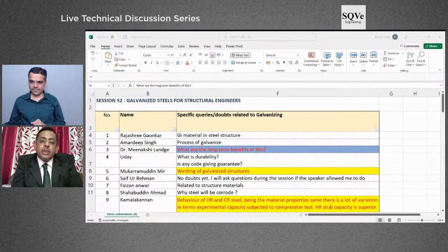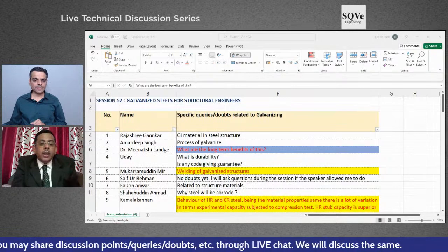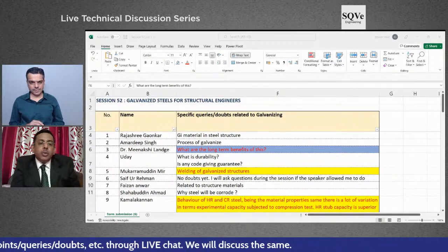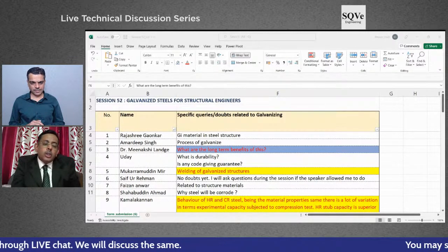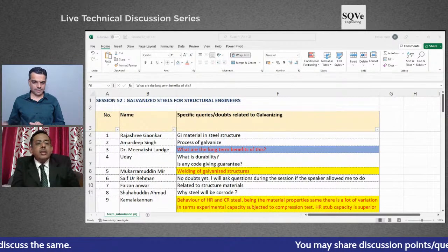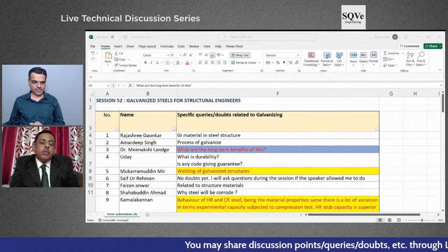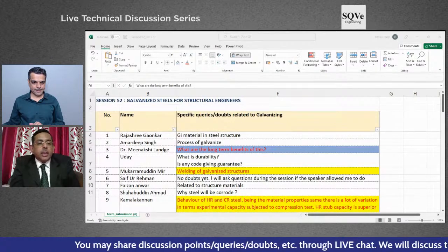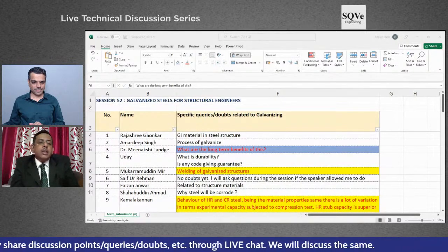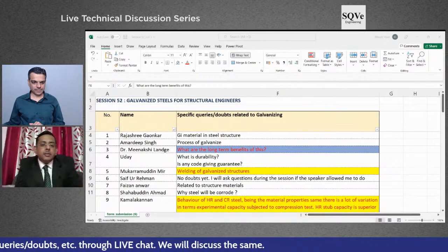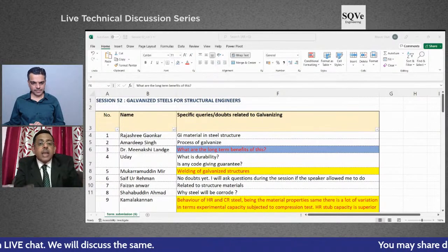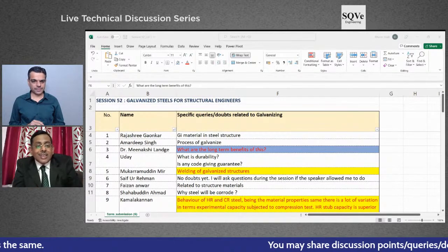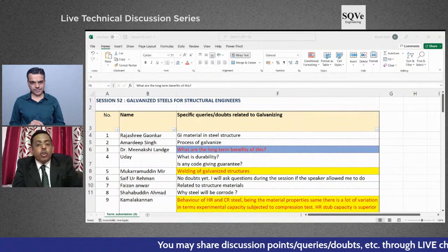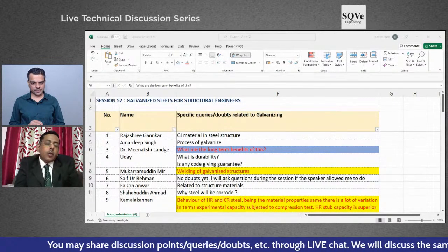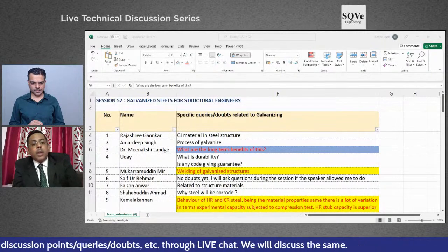Long-term benefit in terms of the protection of the steel, because steel is a very precious thing. You are putting it inside your building, and you don't want to change it every 2 years, 3 years. Steel will naturally degrade against the atmosphere, because atmospheric corrosion will always take place, and nobody can afford changing the steel every 4 or 5 years, because it is a structural part. Galvanizing helps in that area. Galvanizing increases, as per the technicality, your corrosion life by 4 to 5 times. What needs to be replaced in 20 years can be shifted to 60, 70 years.